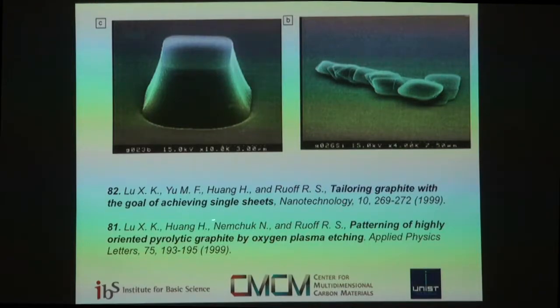We used highly oriented pyrolytic graphite, and I'm just showing you one pillar, an SEM image. My goal here was, if we knew the grain size of the HOPG, to create little pieces of HOPG that were smaller than the grain size. The grain size of this HOPG was roughly around 8 microns. So we would cleave the HOPG, and then spin coat a thick layer of photoresist, pattern the photoresist, put down a mask like silicon or aluminum, and then oxygen plasma etch at the end step. That's a perfect etch stop because it makes the oxide, and so it would remove the surrounding carbon.